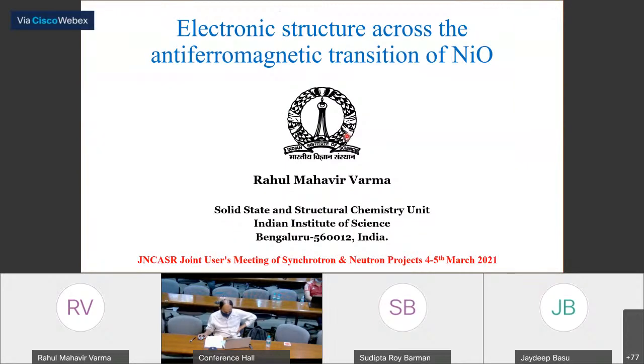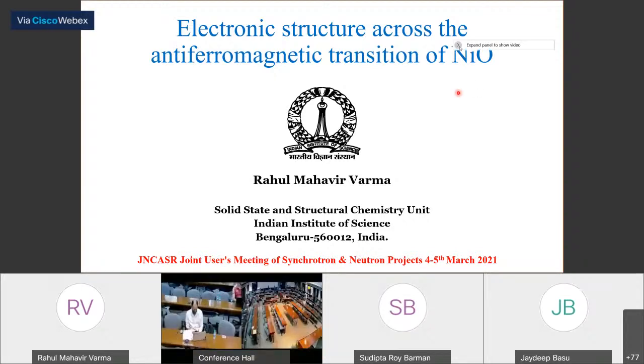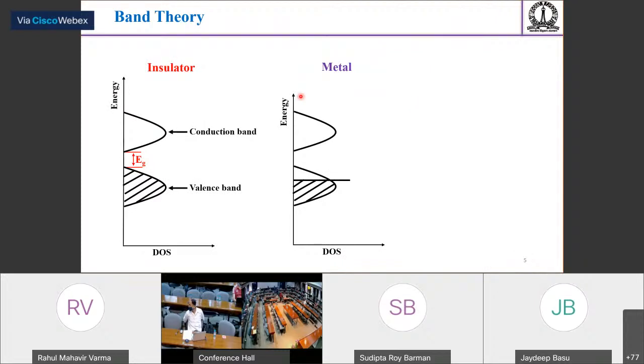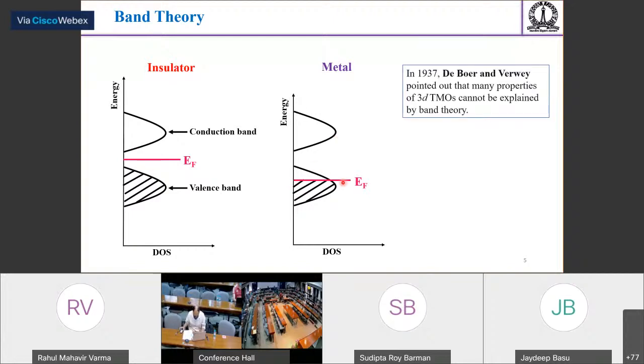So in this work, we are trying to understand whether the magnetic ordering has any influence on the electronic structure across the antiferromagnetic transition of nickel oxide or not. Before going to the motivation and results, I would like to give a brief introduction about nickel oxide. Band theory suggests that for a system to be an insulator, the highest filled band should be completely filled, and for a metal it should be a partially filled band. In other words, the Fermi level will lie inside the band gap for an insulator. In the case of a metal, it will lie inside the band.